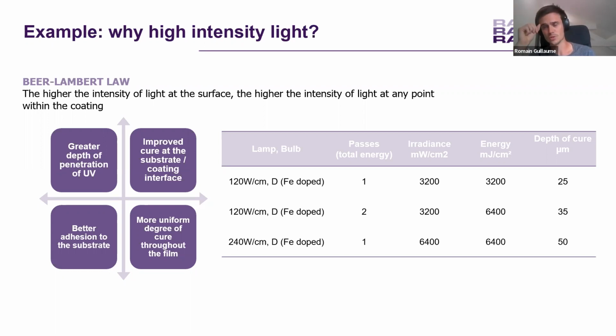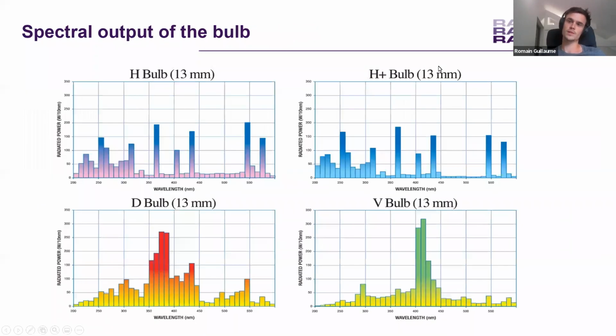So that's something we also have to take into consideration when we define a process. It's not because you have the same energy that you will get the same results at the end of your process. It's also linked to the irradiance, so these two specifications have to be taken into consideration when you want to define the right UV equipment. Then the last one is the spectral output, so the wavelengths of our UV equipment. We know that with the UV mercury medium pressure lamp, depending on the doping of our lamp, we are able to shift the spectral output in order to match better with the formulation of the coating itself.